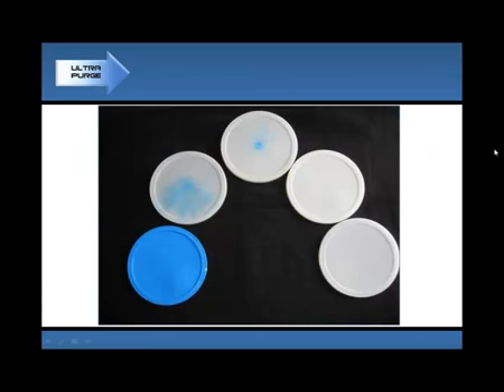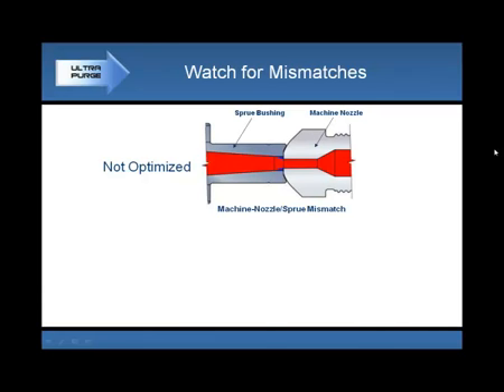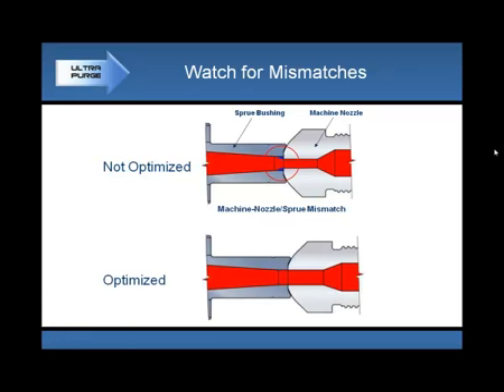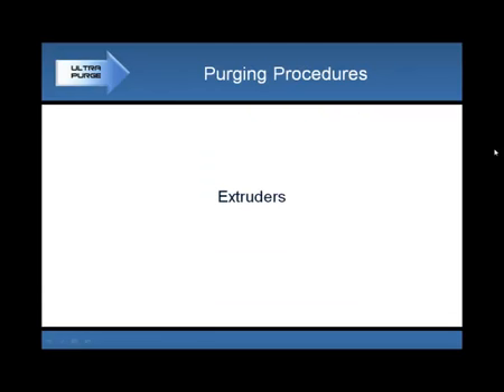We also have a specific grade that we designed for stack mold application. That is 100% moldable, even with the mold that normally run resin with a melt flow of 40, 50, 60, even 80. And this is a new solution that we have developed with one of our customers. And definitely it is very efficient in order to clean the hot runners. The only solution with stack mold is actually to mold parts in order to clean the hot runners. Always watch the mismatch, as we discussed before, in between the nozzle and the mold, basically, in order to make sure that there are no dead spots in there.